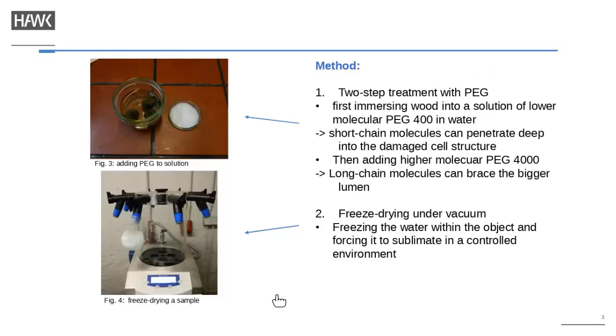The method that's quite commonly used is a two-step treatment, with first immersing the wood in a solution of polyethylene glycol and then freeze drying it afterwards under vacuum. The two-step treatment with PEG is made up of first immersing the wood in a solution of low molecular PEG, in this case 400, in water. The short chain molecules can penetrate deep into the damaged cell structure and fill those smaller spaces.